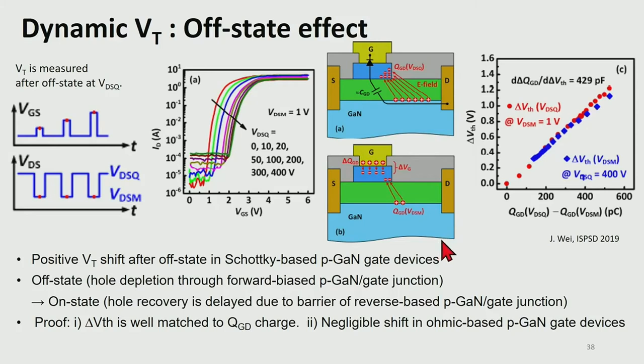VT instability in the P-GaN gate is also observed after off-state stress. So this research investigates the VT shift after high voltage off-state. If you see this left figure, first the devices were stressed in the high voltage off-state, and they came back to the low voltage and transfer curves were measured. And after high voltage off-state, the positive VT shift is observed as you can see in this figure. And the amount of the shift increases with increasing the off-state drain voltage. But what is very interesting is the amount of the VT shift shows a direct correlation to the charge injected to the P-GaN gate during the off-state.